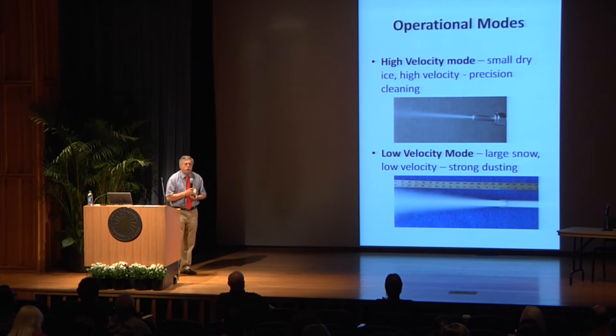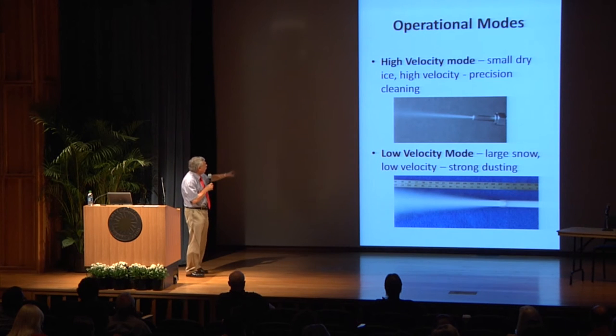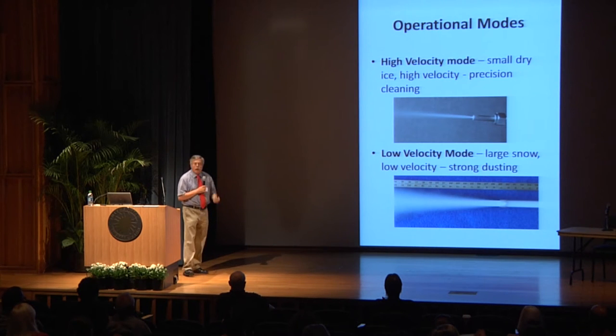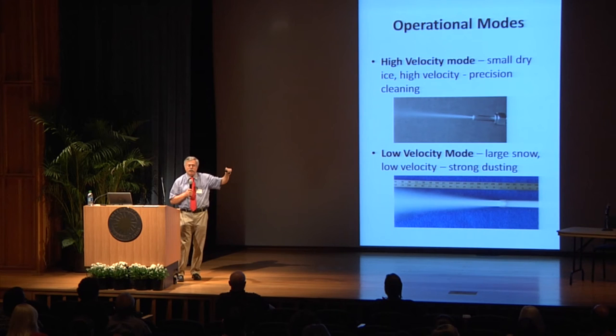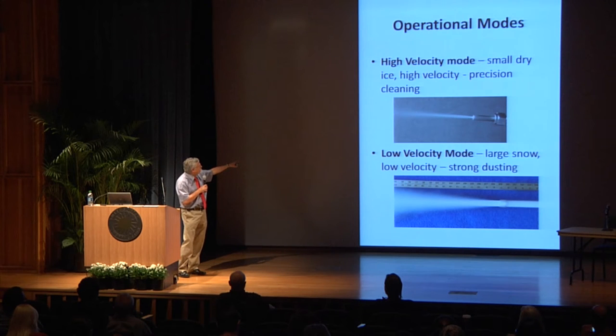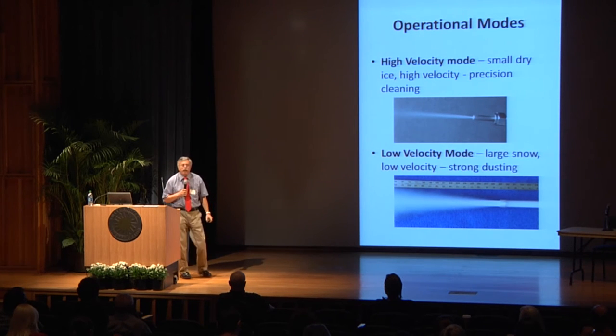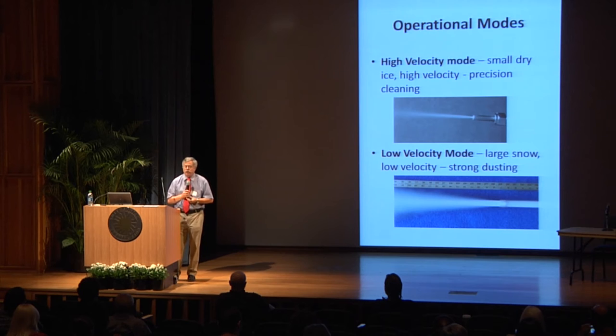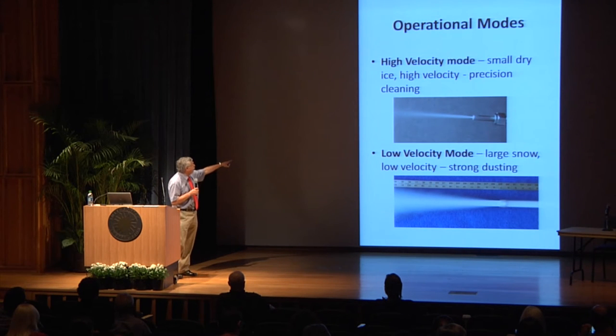So there's two modes of CO2 snow cleaning. And I think the next two speakers are going to be talking about the high velocity mode, where we're going back to that pressure enthalpy diagram. We're using an adiabatic type of nozzle, getting a pressure drop and producing a stream of high velocity, very small dry ice. The size of the dry ice is on the order of 10 to 100 microns. And it goes for about 3-4 inches, maybe up to 5 inches, depending upon the feed and other factors.